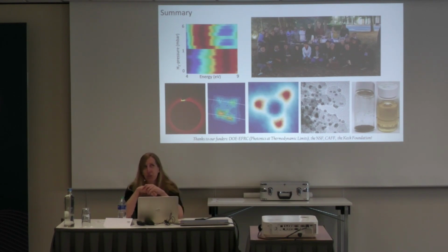And I had another student who was looking at 2-dimensional materials like hexagonal boron nitride and color centers in those. And there we basically used the electron beam as kind of like a white light source, and then could couple light out to be able to understand how the optical properties correlated to the atomic scale structure. So you have it already, basically.